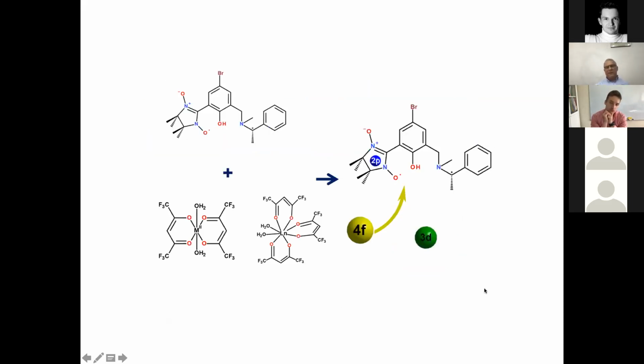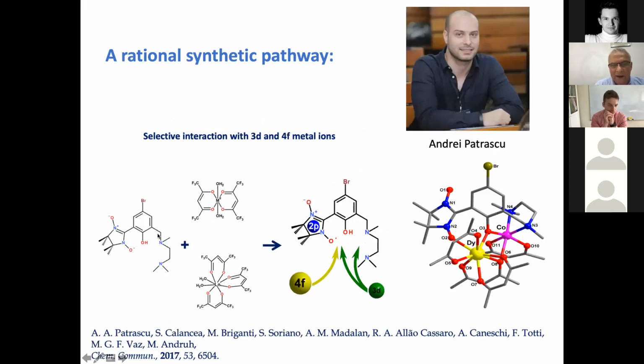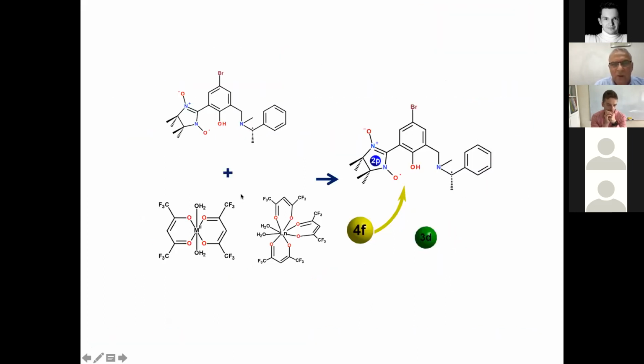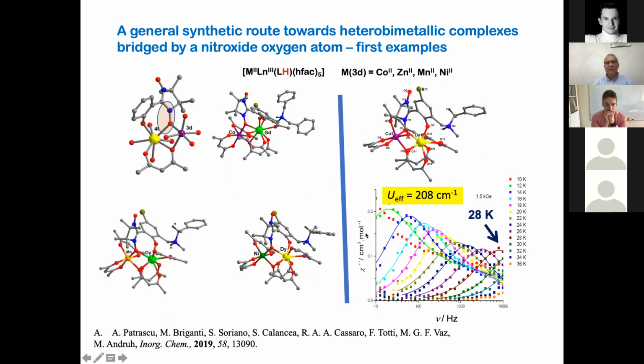And in order to reach this topology, we removed one of the nitrogen atoms from the Mannich arm here. This is a Mannich fragment. And the absence of this nitrogen atom will eventually force the nitroxyl group to act as a bridge between the 2 metal ions. And indeed, it was successful. We have the first examples here of systems where the aminoxyl group connects 2 different metal ions. So the procedure is general, irrespective of the nature of the lanthanide or of the 3d metal ion, cobalt, manganese, nickel, and so on. And the strategy works, and this was published 2 years ago.